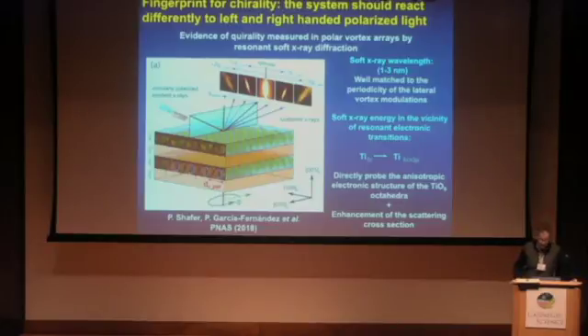So in the last couple of minutes, that's the theoretical predictions. The fingerprint for chirality would be a different reaction of the system under different circularly polarized light, left or right-handed. And this was precisely the experiment that was carried out in the group of Professor Ramesh at the University of Berkeley, where they were using soft X-ray diffraction.